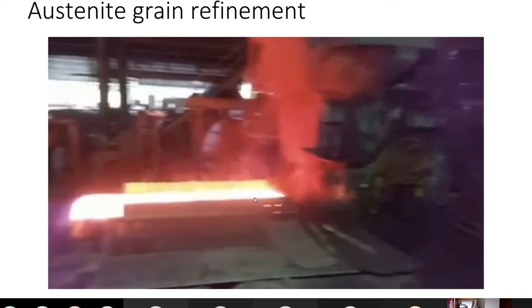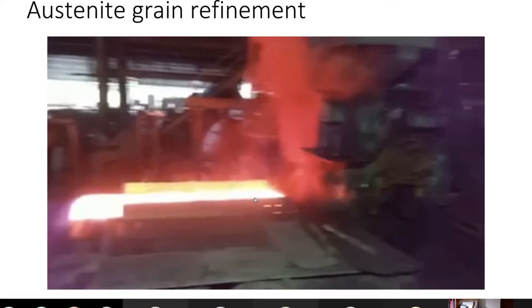You put in some sort of particles — very commonly niobium carbide, because the hot rolling is at a high temperature and you can get the niobium carbide to precipitate at high temperature. That stops the austenite grains from recrystallizing.